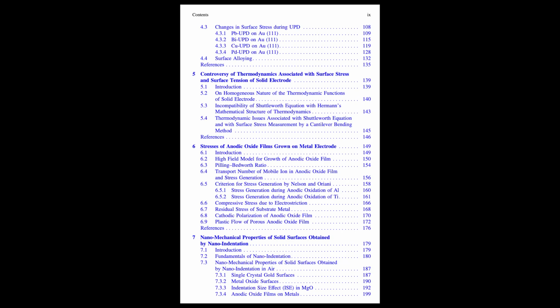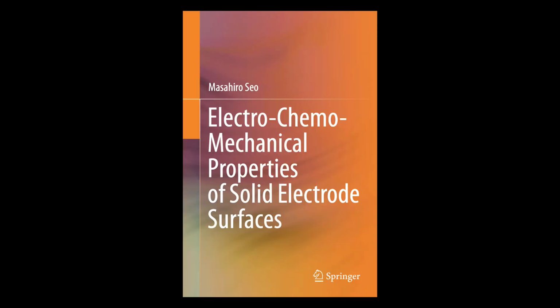And that shrinking must affect the stress, I'd guess. It certainly does. Generally, larger atoms cause compressive stress, right? If their effective size shrinks during alloying, that can partially relieve some of that compressive stress. We see evidence for this in systems like lead and tin on nickel electrodes. The measured distances between atoms in the surface alloy are shorter than simple hard sphere models predict. Okay. But conversely, if the adsorbate atom is smaller than the substrate atom, like copper on tungsten, surface alloying can actually increase tensile stress, pulling things apart more. So it really depends on the relative sizes and how they accommodate each other at that interface, whether alloying squeezes more or pulls more.